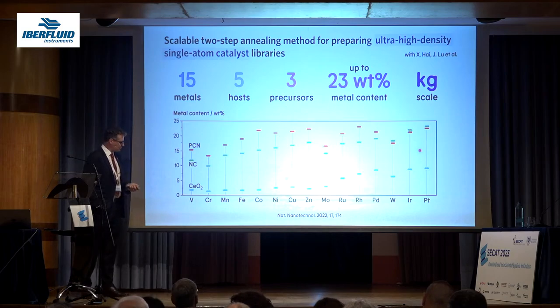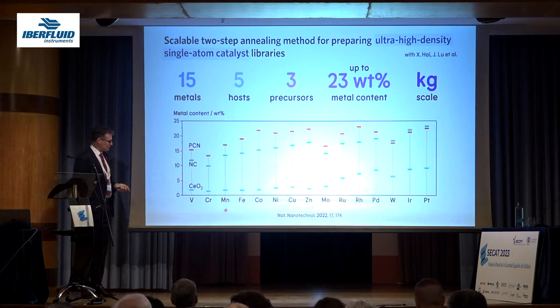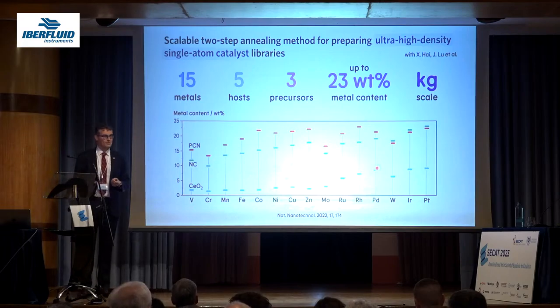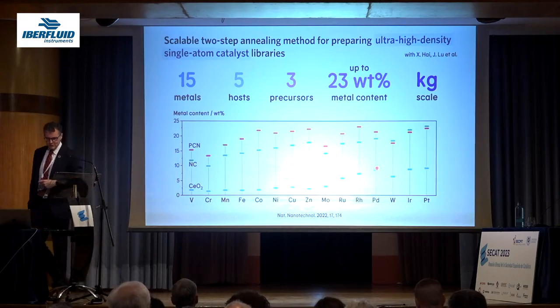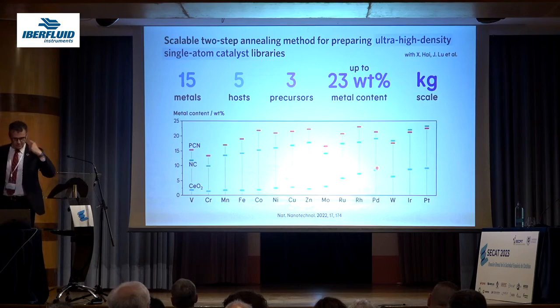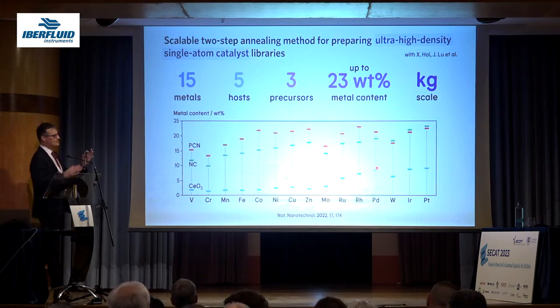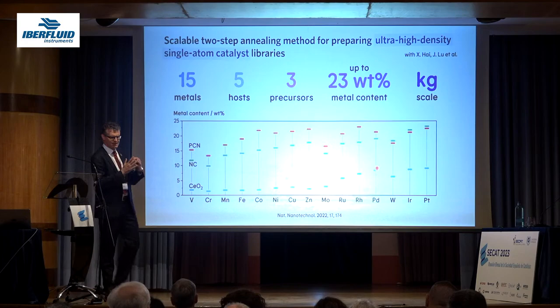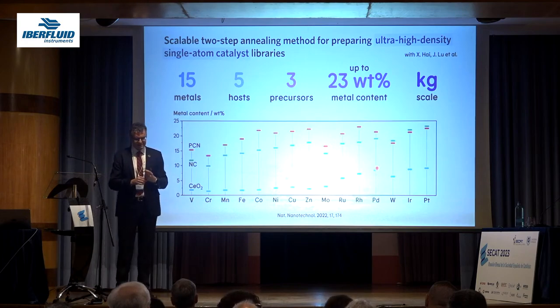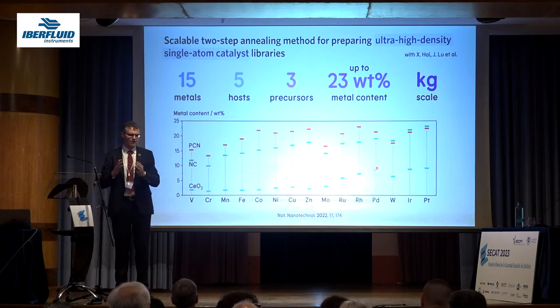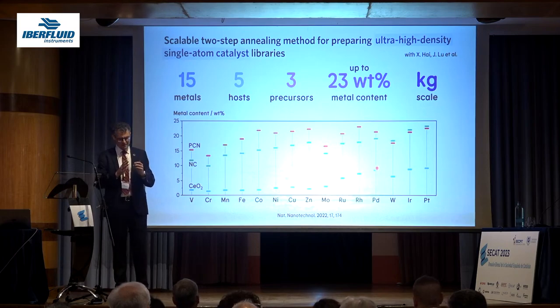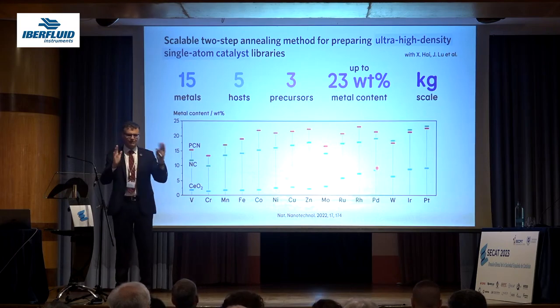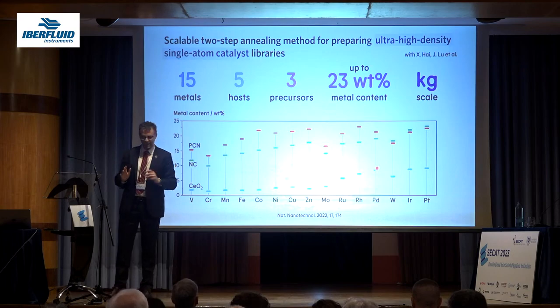For inorganic supports, like ceria, you could also do a decent job. In some cases, you can go up to 10%. It's a very high loading. And so then the notion that came when we published this recipe, which is a two-step annealing process, it's very scalable. It's a two-step impregnation, if you like, with thermal treatment in between. Nothing fancy. It can be scaled up.